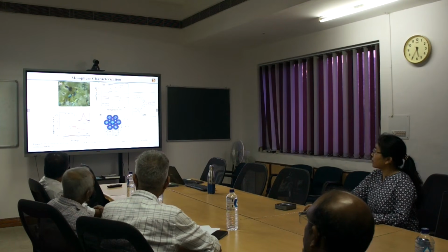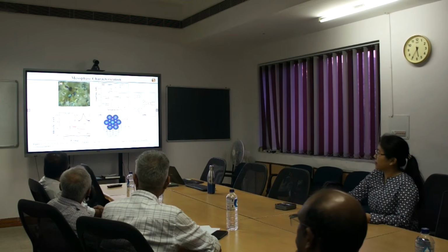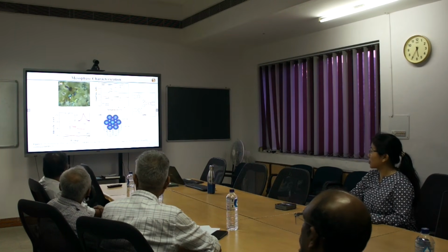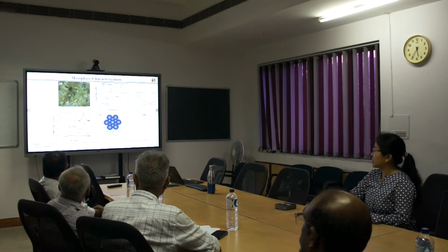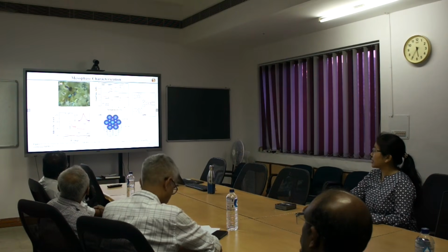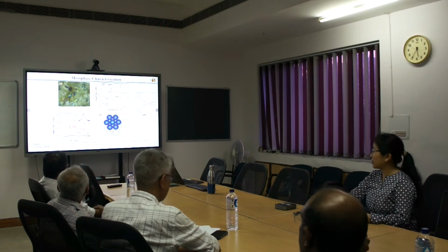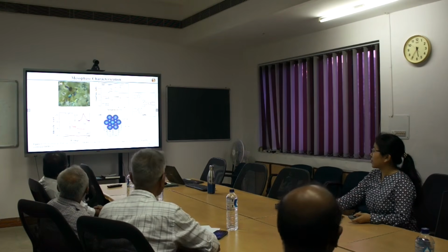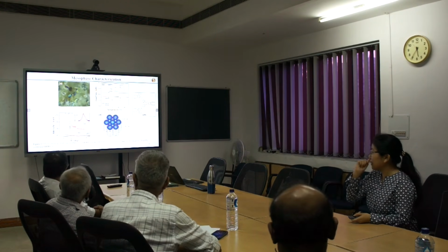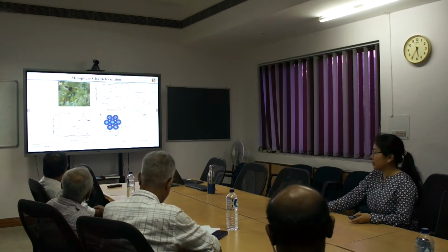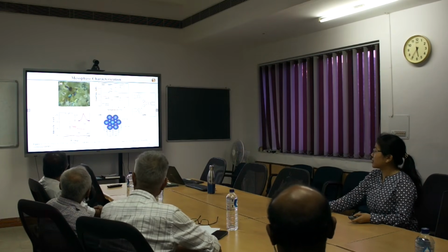But for QER1, where three alkoxy chains are present, this birefringence texture was observed, and from DSC, we can see that the isotropic temperature was around 34 degrees Celsius, and in the DSC cooling curve, the transition from the isotropic to the mesophase state was not that clear. However, from the XRD studies, we observed an intense peak corresponding to Miller index 10, and two peaks in the wide-angle region corresponding to the peripheral alkyl chain and the pi-stacking.